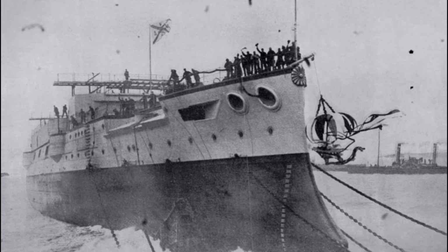Between June 1944 and the war's end in August 1945, 531 Victory ships entered operation, and not one suffered catastrophic hull failure. Only a handful showed small cracks, which inspectors caught and repaired using the same stress relief techniques before they spread. These ships returned swiftly to duty. The contrast with Liberty ships was total and devastating.